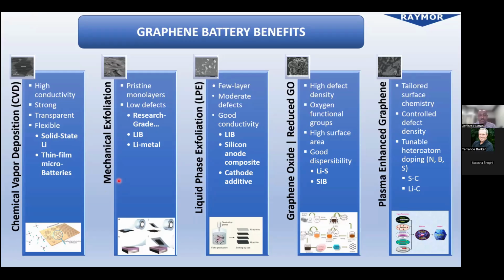For graphene produced by mechanical exfoliation, it's been beneficial to research grade lithium ion batteries and lithium metal batteries. For graphene produced by liquid phase exfoliation, it's found great usage within lithium-ion batteries, silicon anode composites, and in cathode additives. And graphene produced from graphene oxide has found great usage within lithium sulfur batteries and sodium ion batteries. And lastly, plasma enhanced graphene has been quite effective within supercapacitors and lithium ion capacitors.